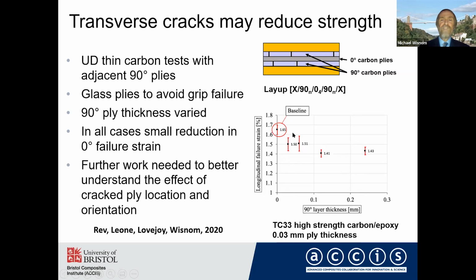And all these results are slightly reduced. And perhaps what's more surprising about this to me is that these ones here are very thin, and actually the transverse cracking was largely suppressed. These thicker ones here, we've got definite transverse cracks, but all of them actually showed a small decrease in the failure strain. So I think this is still an area which needs a bit of further work, because this is slightly inconsistent with what I was showing before.